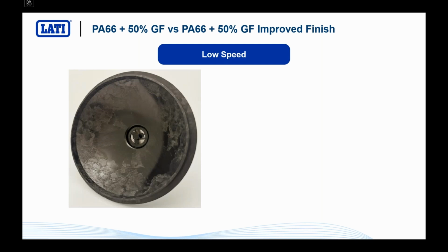This is the typical surface finish of a 50% glass fiber general purpose material, the kind you can use for more or less everything. Low speed with a 3 submarine gate. The surface is the worst you can actually imagine.